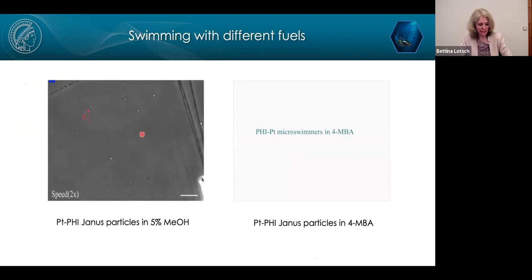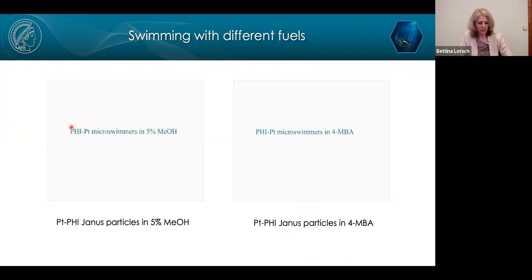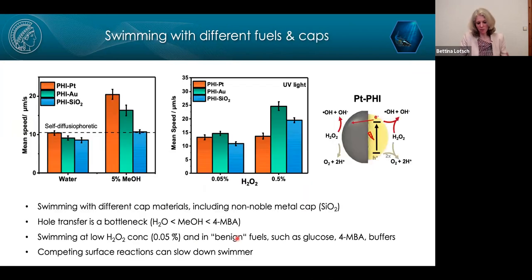And what we see is that, in fact, if we shine light on these particles, I hope you can see the movie. So this is now in 5% methanol. These particles swim. So there's clearly light-induced swimming possible by using various electron donors, methanol or 4-methylbenzyl alcohol, and of course also hydrogen peroxide, but at very low concentrations actually. So this is a very dense slide.